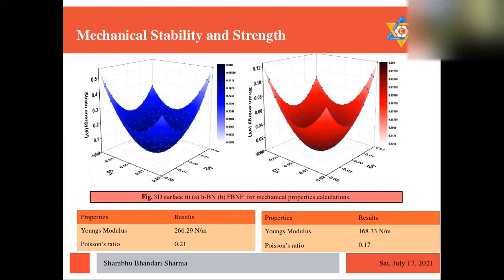And further, we calculate Young's modulus and bulk modulus and Poisson's ratio for both parameters, both monolayers and we tabulate there in table. And we can clearly see that the mechanical parameters is reduced, especially the Young's modulus and Poisson's ratio both is reduced after fluorination.